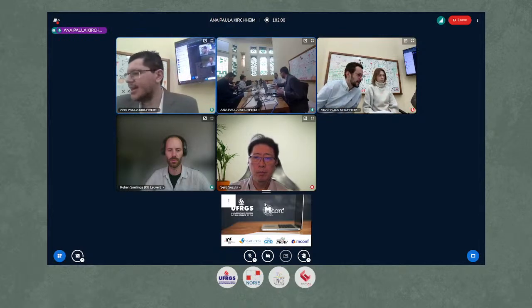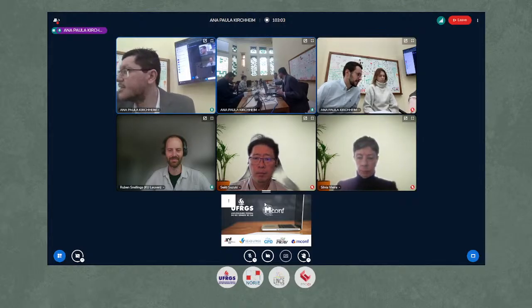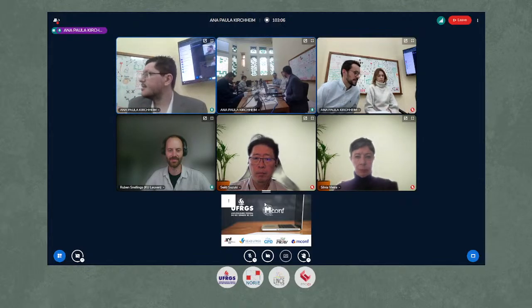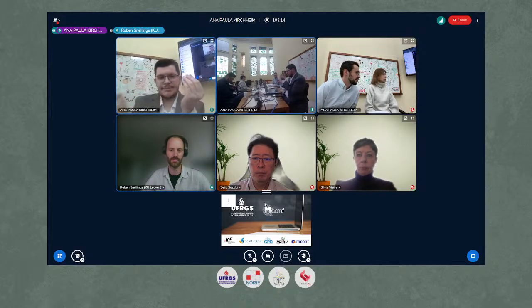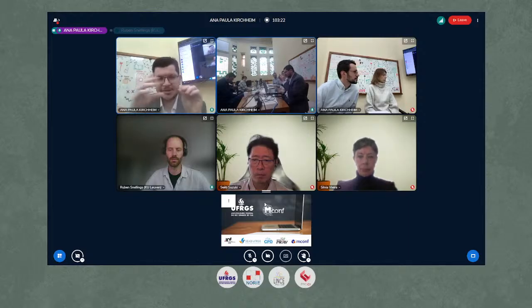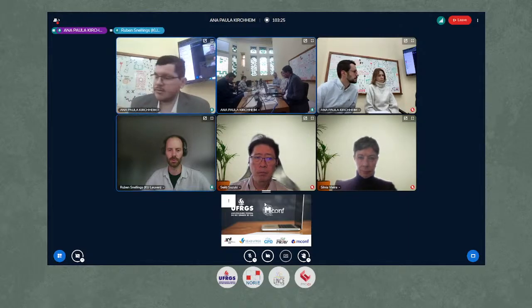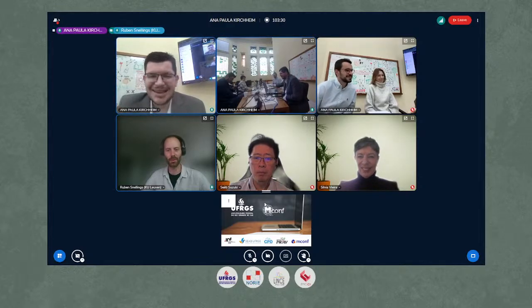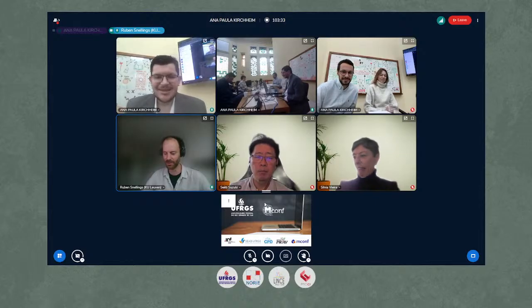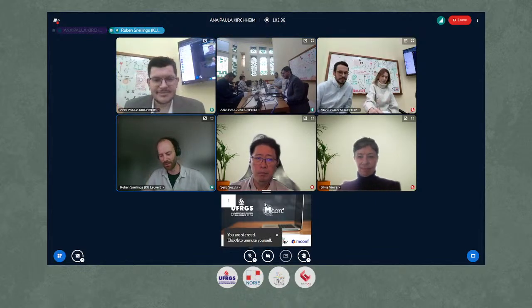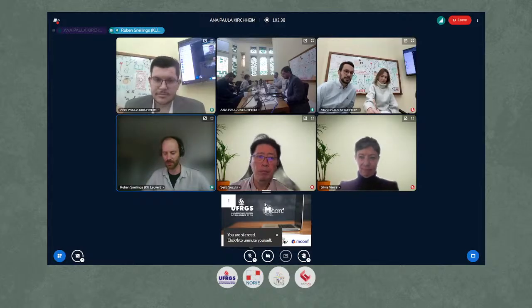Sorry for interrupting, Ruben. In the synchrotron measurements, there was no specific device, but the measurement was quick, like 1 minute. And they changed the sample, and the whole room was 21 Celsius degrees. Yeah, but you didn't have a sample holder temperature control. It was only 1 minute, so more or less 21 degrees, approximately the same. Yes, just be careful that it's not too different, because then things of course start shifting.